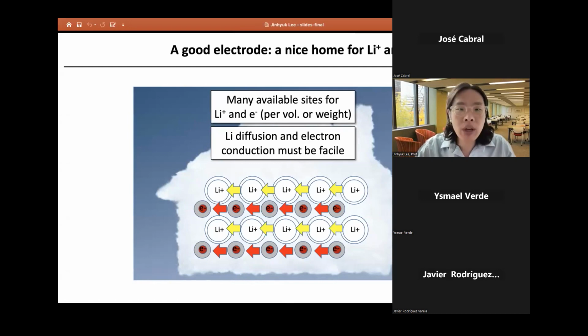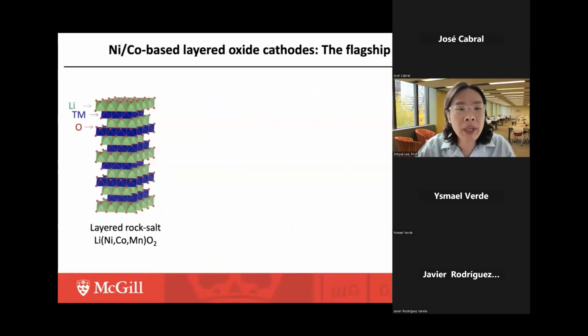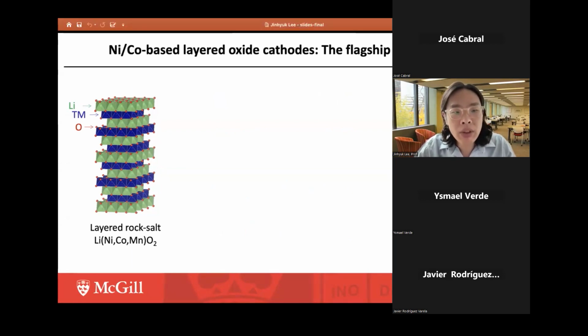In this respect, there has been a legendary class of cathode materials from which nearly all high-performance cathode materials have been developed for lithium-ion batteries, which are called layered rock salt type lithium transition metal oxides, in particular those that utilize nickel and cobalt as the main transition metals. In these layered oxide materials, lithium and the transition metal form alternating layers within the cation sublattice, and the oxygen forms the close-packed lattice.